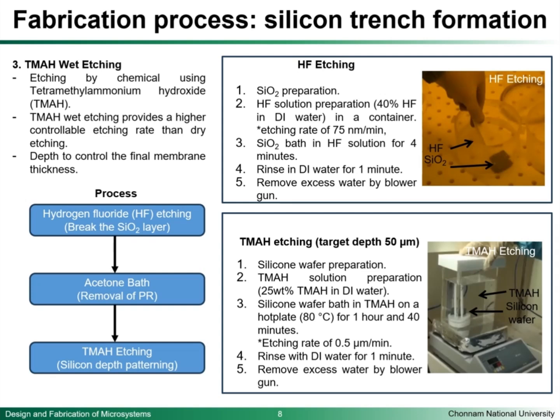And then we will heat it up on the hot plate at around 80 degrees Celsius for about 1 hour and 40 minutes. And for information on the etching, for this concentration, the etching rate is around 0.5 micrometers per minute. And after it is finished, we will rinse it with DI water for 1 minute and also remove the excess water with the blower gun.